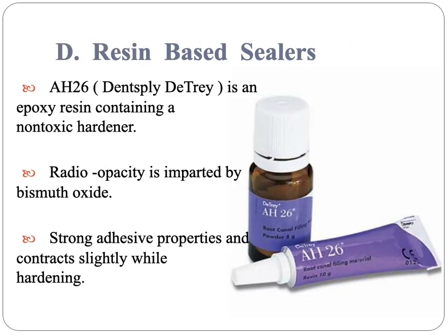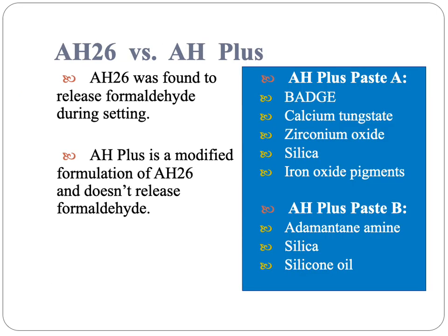And at last, we move on to the resin-based sealers. So the one trademark is the AH26 by Dentsply. It is an epoxy resin containing non-toxic hardener. The radio opacity is imparted by bismuth oxide, as in all the sealers. It has good adhesive properties. It contracts slightly while hardening. The only thing is the dimensional stability is a little bit lower compared to other sealers.